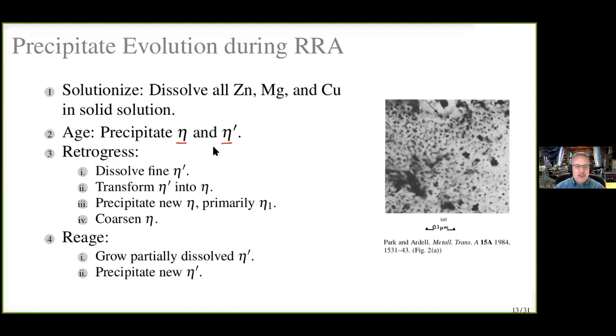Now, what the retrogression heat treatment does is at first it dissolves the finest of the eta prime particles. Slightly coarser eta prime particles are transformed to eta. Some new eta precipitates are formed, usually of the eta 1 variety. That's one of the three varieties of eta that were observed. And some existing eta precipitates are coarsened, particularly at grain boundaries. Now, the reaging heat treatment, which is at 120 Celsius for maybe 24 hours for best reaging, partially dissolves eta prime precipitates and precipitates new eta prime precipitates.